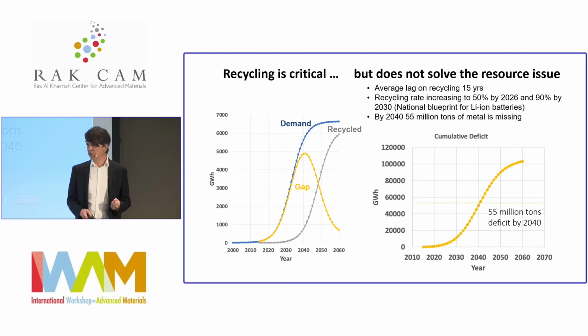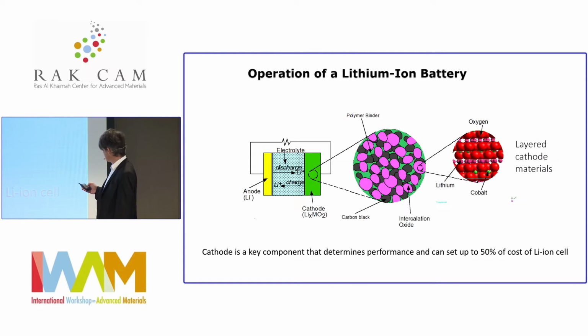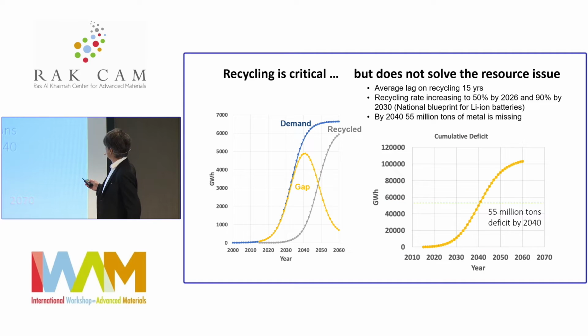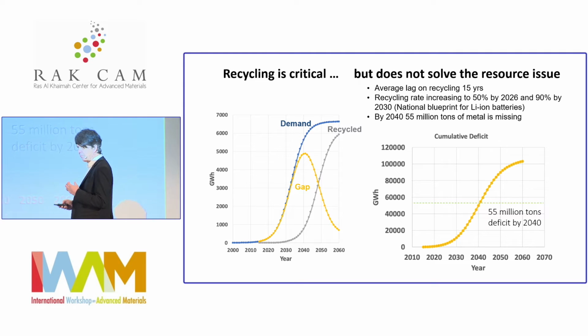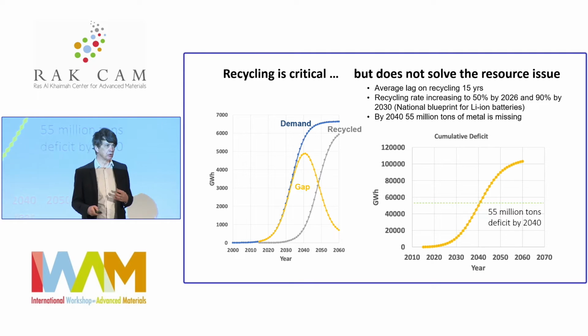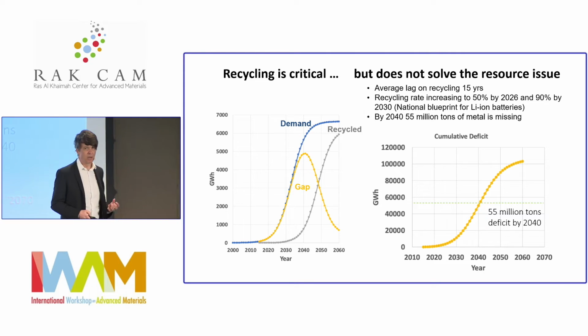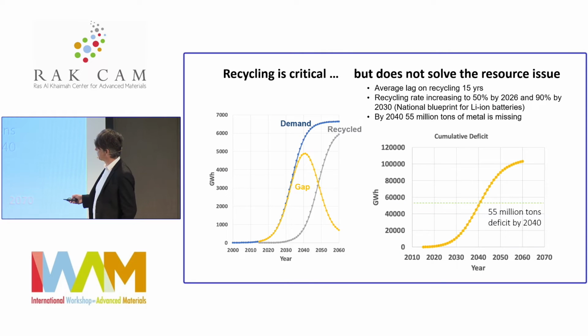You are going to use that for second life, and what that means is that the lag on recycling, meaning the lag from between when the battery was put in production to when it comes back into the metal stream, could be as much as 15 to 20 years. What that means is that if you look at the demand curve, and then when recycling comes back and helps you out, there's this enormous gap.